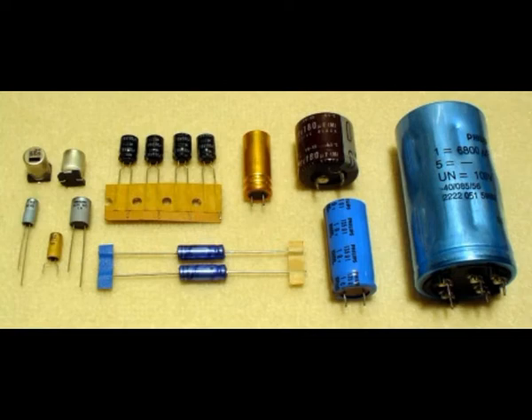Field failure rates for aluminum capacitors are in the range of 0.5 to 20 FIT. The data for the failure rate specification are based on the results of lifetime testing, endurance testing. In addition, a field failure rate is sometimes specified. This figure comes from big customers that noticed failures in the field out of their application. Field failure rates could have much lower values. For aluminum electrolytic capacitors they are in the range of 0.5 to 20 FIT. The field failure rate values are in line with the usual orders of magnitude for electronic components.